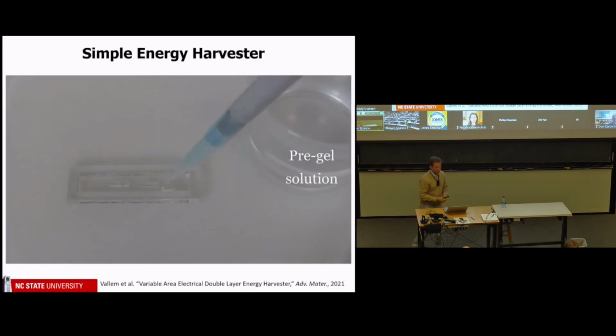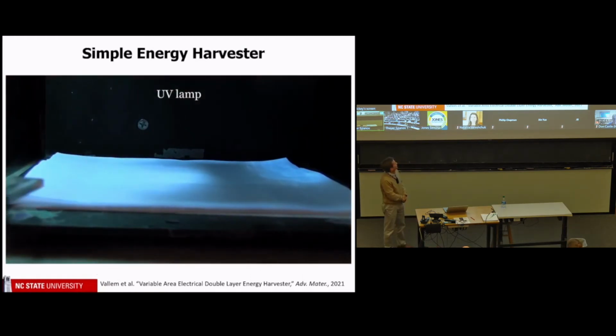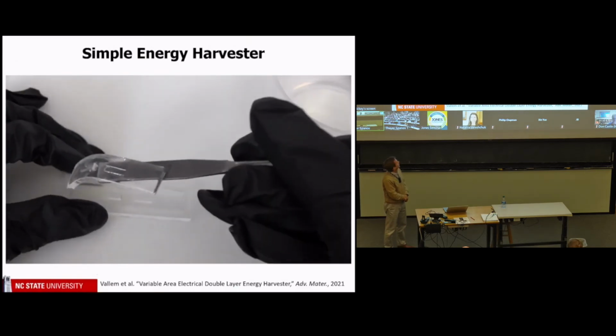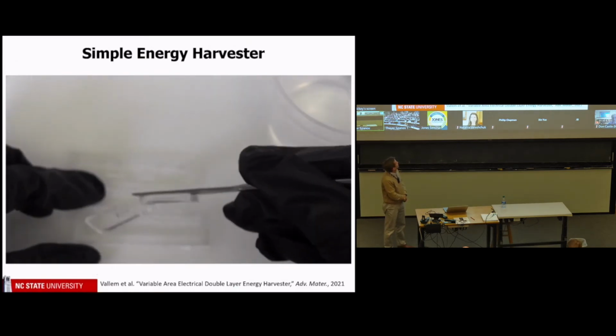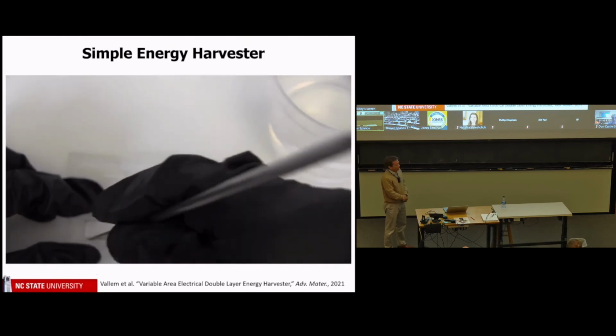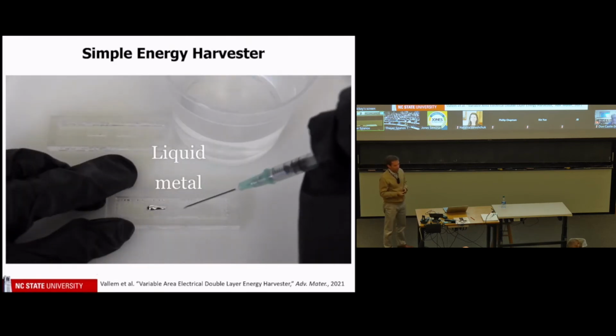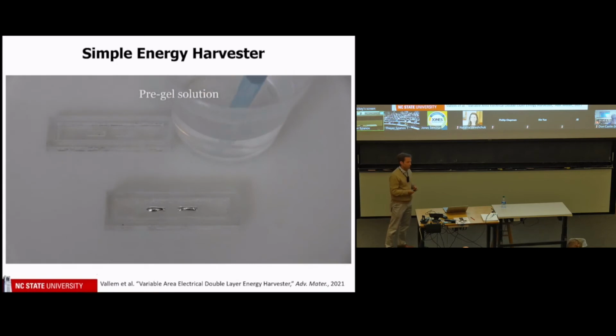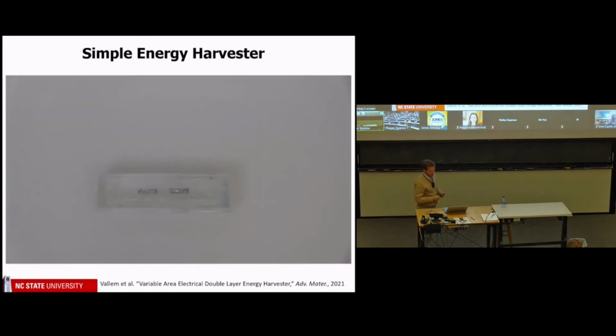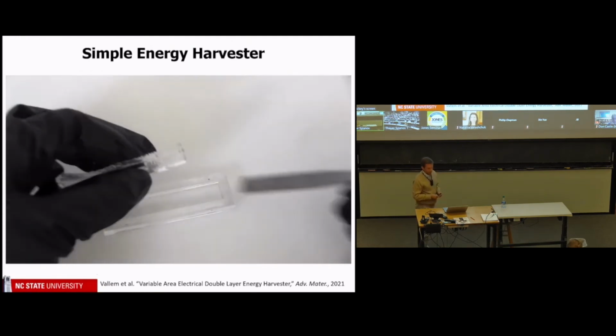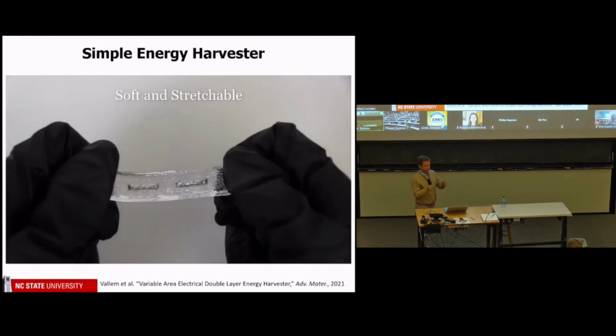And these are very easy to make. We take hydrogel solution, which is just water with some monomer. When we shine light on it, it polymerizes and becomes a gel. You see we've molded it. Then in that molded structure, you can inject the liquid metal just from a syringe. You put more solution to encapsulate it completely, shine light, it polymerizes, and then you're done. The cool thing about this is it's very soft, and you can stretch it, bend it, twist it, compress it. Any mode of mechanical deformation will change the area of that metal gel interface.